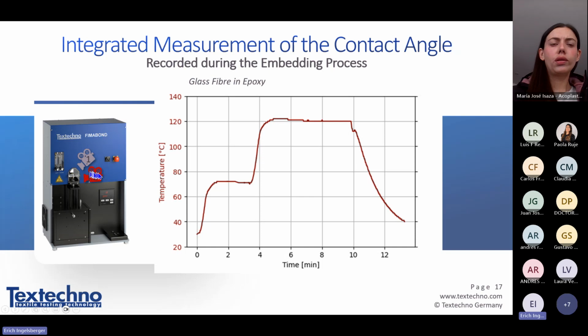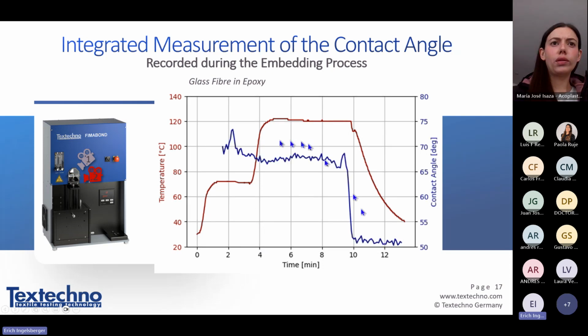As I said, we can measure the wetting angle with the second camera, and we can now see both curves in one. You see here, this is the moment where the fiber is embedded, and you see the contact angle or embedding angle here. During cooling down, the angle moves or returns, reduces. This means there is a certain shrinkage of the epoxy while cooling down.